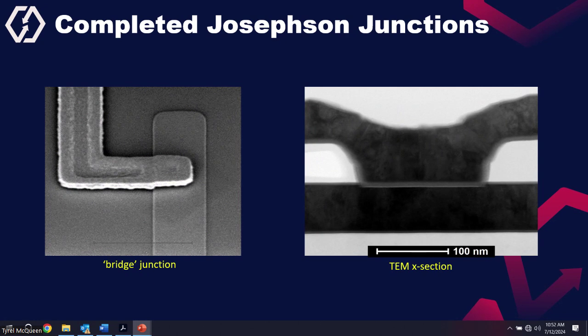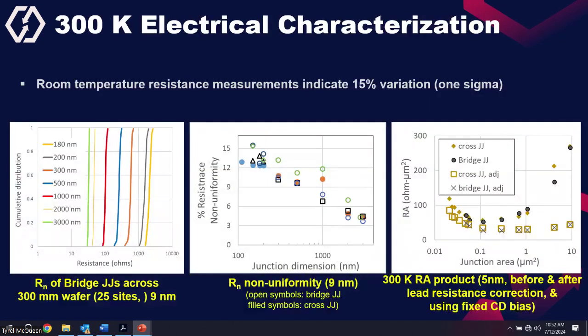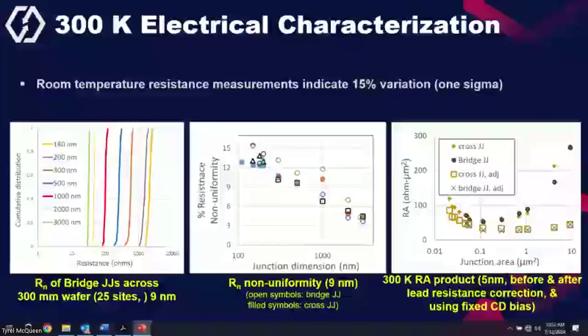So now we have completed the Josephson junction fabrication. Next step is to determine how good our junction is. And for that, we do electrical test. The left-hand side graph shows the cumulative distribution of resistances for junctions with different dimensions. These are square junctions, from 180 nanometer by 180 nanometer to 3 micron by 3 micron. Here we see that the resistances are changing as a function of the area, which is as we expect. And next, it shows how the resistance non-uniformity is varying as a function of junction dimensions,